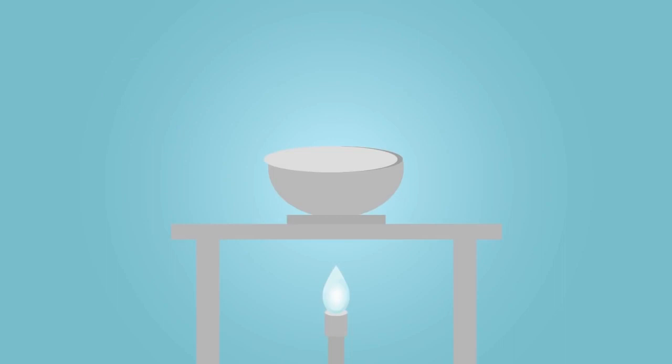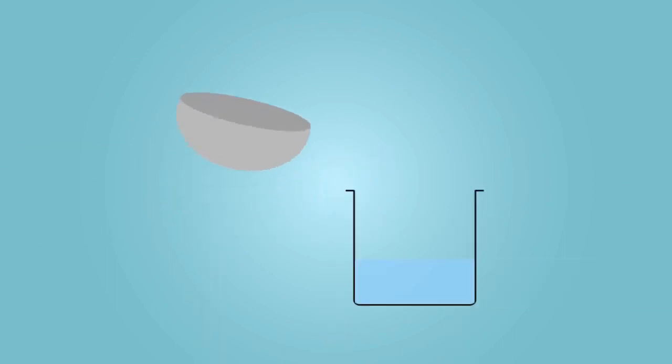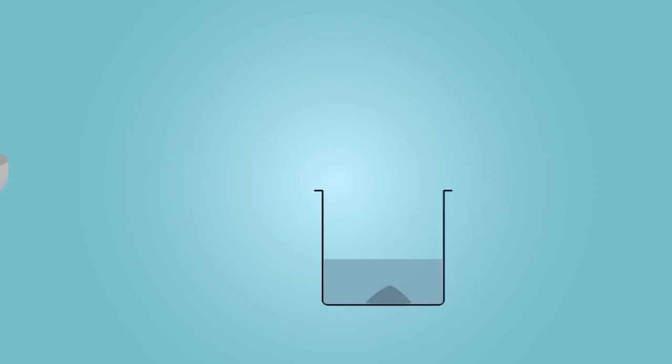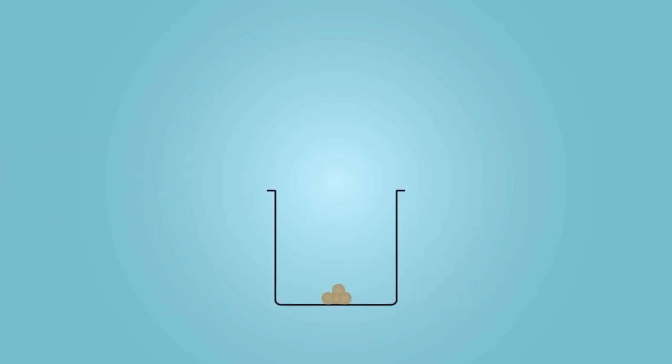Remove the crucible from the Bunsen burner and empty its contents into a beaker of cold water. Pour out the water and charcoal, rinse with water and repeat. This must be done when the mixture is hot, or else copper 2 oxide will reform. You will find little bits of copper metal at the bottom of the beaker. You have successfully extracted copper metal.